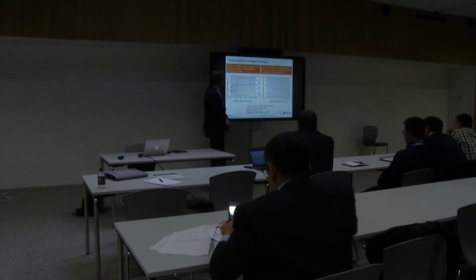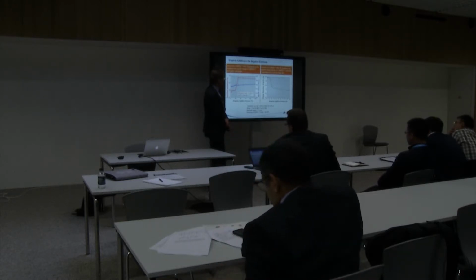When optimizing the electrode resistance, there is always this interplay between electrical and ionic resistivity. And I put this slide as an example. You see here a negative electrode, and the electrode resistance of this negative electrode is measured by measuring the direct current resistance in a symmetrical cell at 50% state of charge when applying a 1C current pulse at 20 seconds. So the electrode resistance, when adding graphite conductive additive into the electrode, is decreasing and then sharply increasing.